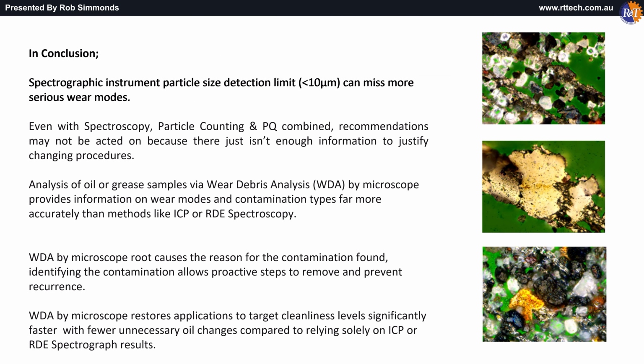In conclusion, a spectrographic instrument particle size detection limit of less than 10 microns can miss more serious wear modes. Even where spectroscopy, particle counting and PQ combine, recommendations may not be acted on because there isn't enough information to justify changing procedures. Analysis of oil or grease samples by wear debris analysis by microscope provides information on wear modes and contamination types far more accurately than methods like ICP or RDE spectroscopy.